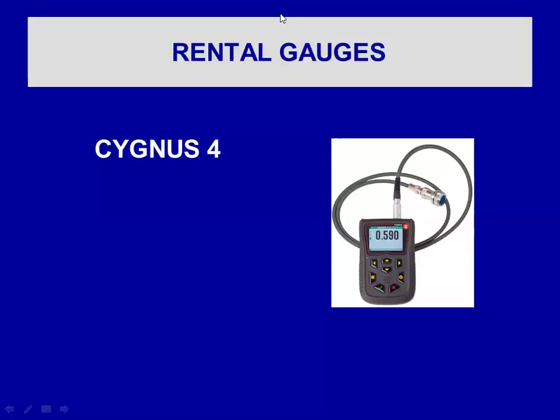If this isn't enough, mark the pipe and go get a flaw detector. Go get a radiographer. Go get somebody to take a picture of it. Do something else. Thickness gauges are only thickness gauges. They're not designed to look at discontinuities and cracks and all that sort of stuff. They give you an indication. Like I say, with ours, the indication is that it won't get you in there. It measures here, here, here, but won't measure here. Well, why won't it measure here?